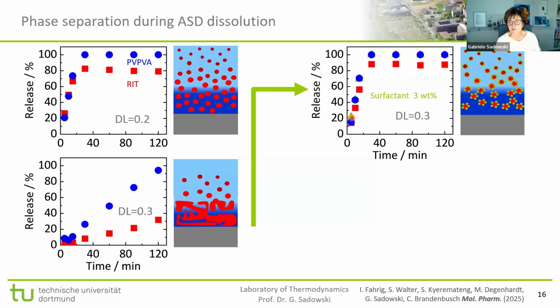Once we add surfactants to the system, the surfactants also release, these other triangles, the green triangles you see here. They are here behind the blue symbols, meaning that the surfactant is also totally released. You can see here that it's in the system, so it's also what we monitor. And the idea is that adding the surfactant stabilizes the small droplets of the Ritonavir-rich phase. So we have a morphology very similar to the one at low drug loads, and so we also have a similar release behavior.